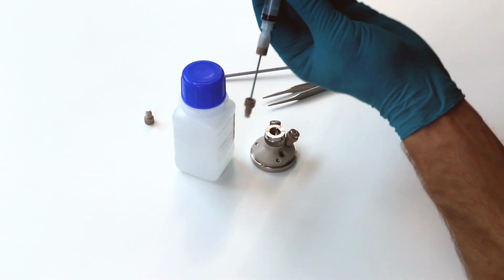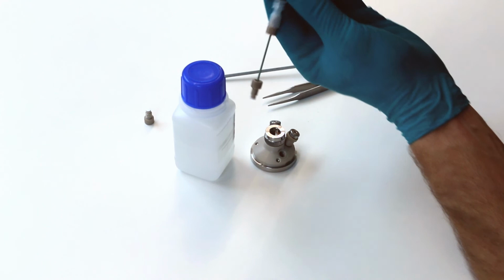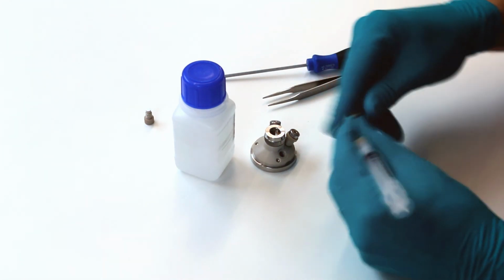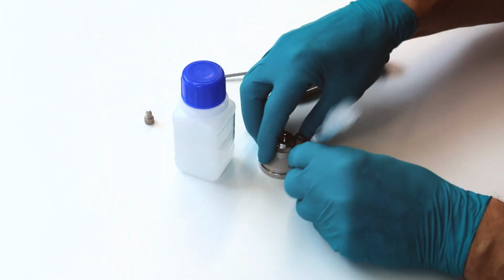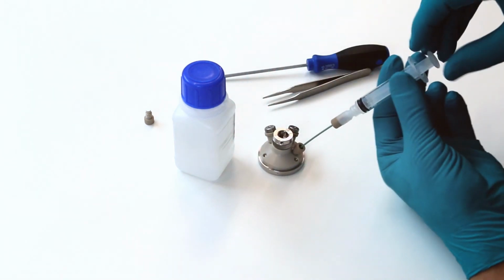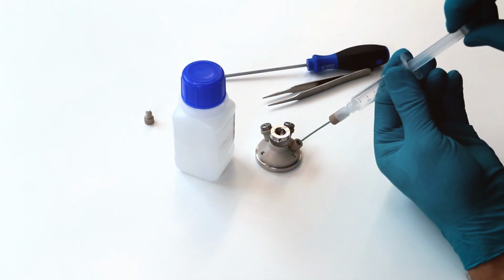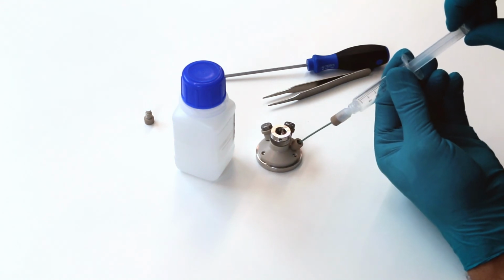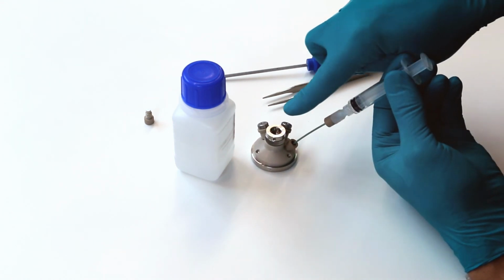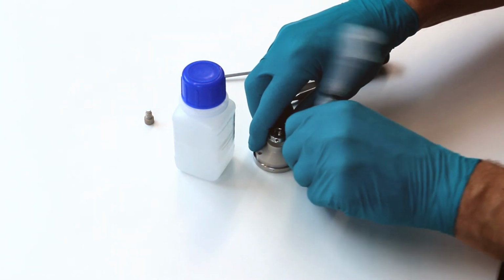Take up a small amount of electrolyte, approximately 0.2 milliliters, with a syringe. Attach the syringe to the ref port of the test cell, pull back the syringe piston in order to evacuate the cell, release the piston so that electrolyte goes into the cell, then remove the syringe and plug the cell.